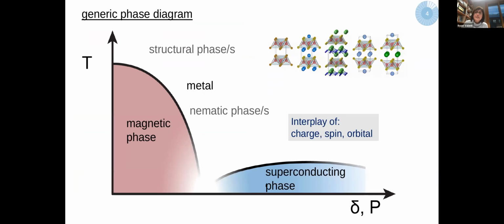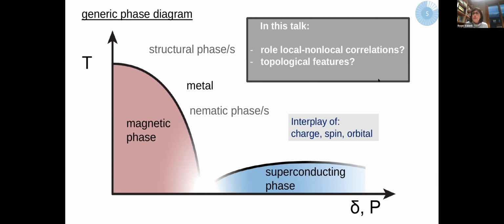So if we consider the generic phase diagrams for the iron-based superconductors in a temperature versus doping or pressure representation, we know that we have a superconducting phase in the vicinity of some magnetic phase or phases, nematic phases, and structural phases. Over the years, new types of phases have been coming into these complex phase diagrams, which are a consequence of a subtle interplay of charge, spin, orbital, and lattice degrees of freedom. What I want to concentrate on today is the role of local versus non-local correlations in some of these phases, as well as possible new topological states that can emerge in these materials.